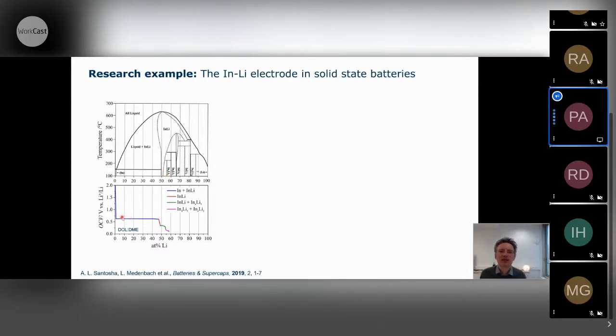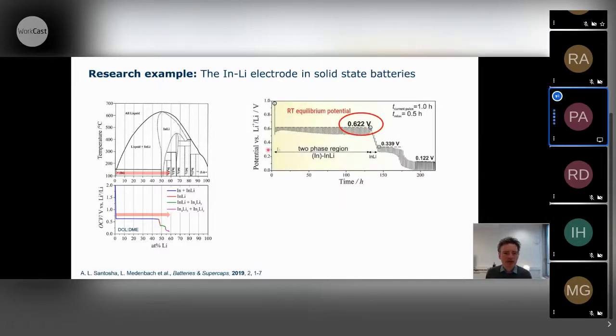And you can always monitor the electrode potential during this experiment. You can see here, as long as you're in this two-phase region between this indium-1, lithium-1 alloy and the pure indium, you have a very constant voltage at around 0.6 volts. And if you go further, then the voltage drops. So you can see how the phase diagram directly relates to your redox potential. These are the underlying measurements. We obtained these results with relaxation measurements. And indeed, we found at room temperature the equilibrium potential of the lithium-indium electrode, as long as you're in this part of the phase diagram, is 0.6 volts.